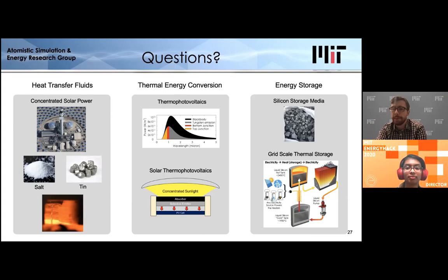Yeah, so basically the conversion of electricity to heat is almost 100% efficient. And then we estimate we lose only about 1% per day in parasitic heat loss through the walls. So the round trip efficiency, as it's often called in the storage field, is really dominated just by the heat to electricity conversion. So we estimate around 50%.